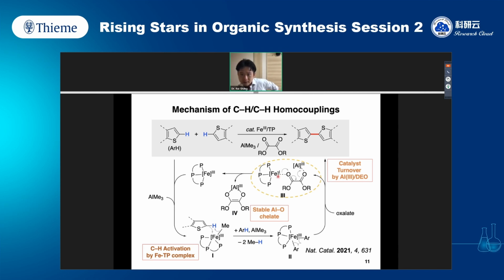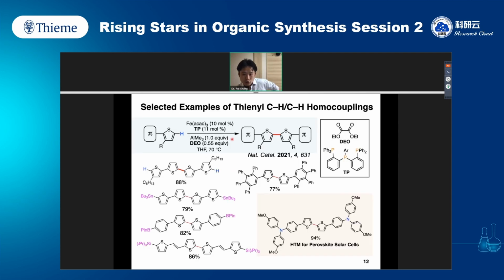But the key is that the catalyst turnover by an aluminum oxalate complex results in the generation of a very stable aluminum enediolate species. This step turns the iron species back to valence 3. But this oxidant is not essentially oxidative towards other substrates, even the donor substrates. On this page, I will show you some representative examples. The reaction has very high regioselectivity. It only takes place at the C2 position of the thiophene, and remarkably, it tolerates the aryl-tin bond. Of course, it also tolerates aryl-boron and aryl-silane, and this reaction is totally orthogonal to the Stille reactivity.